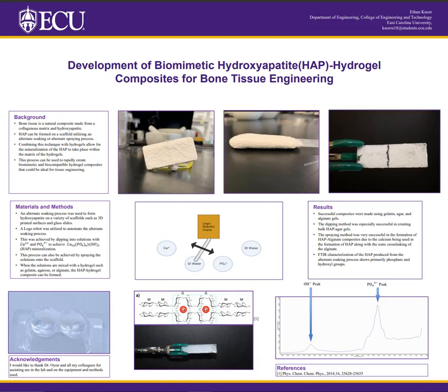To the right of that shows the FTIR characterization of the hydroxyapatite coating formed from the alternate soaking process. As you can see from the spectra, there are clear hydroxyl and phosphate peaks shown. Calcium does not show up on FTIR, which explains its absence from the spectra.